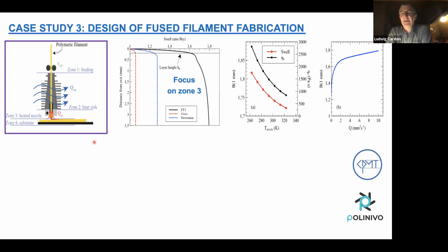So what we try to investigate also in this case, from experience from standard extrusion, is, as you can see, the distance from the exit. So this means when we would have a free flow of material underneath the nozzle, not on a substrate itself. So when we extrude the material, what happens with your material in the scope of die swell due to, let's say, a kind of latent internal pressure in the material. So depending on the distance and depending on the different type of models, the PTT or Cross model or Newtonian model, we try to mimic the die swell that happens in this kind of micro devices.